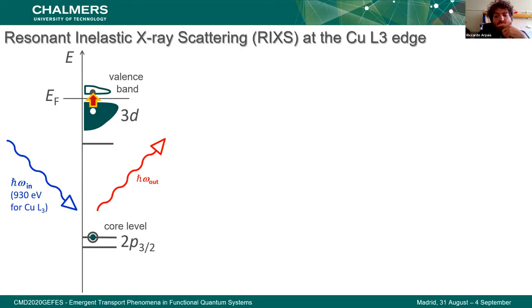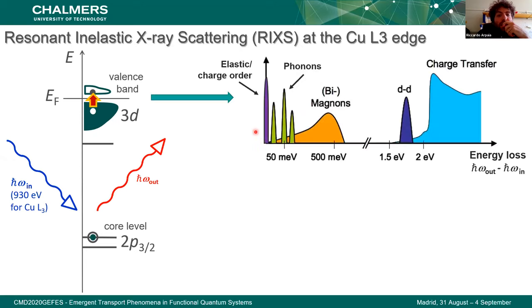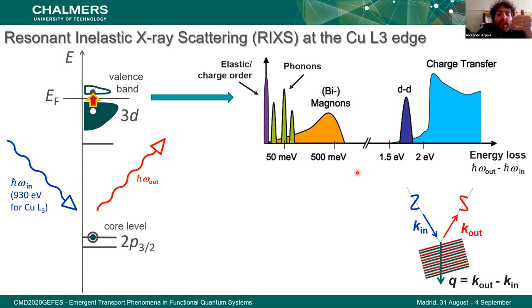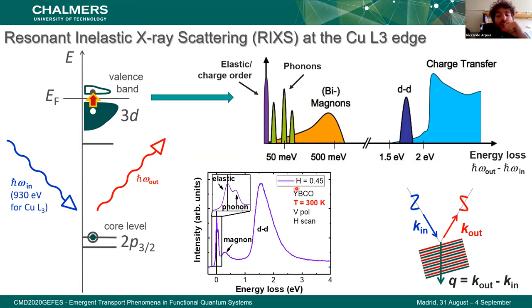Depending on the energy loss between the incoming and the emitted photon, we can study different excitations. In particular, if the scattering process is elastic, we can have access to excitations that are due to charge, so to the charge order. Vice versa, from the inelastic part of the spectrum, we can have access to several excitations: of the lattice, the phonons; magnetic, the magnons; and orbital, so the excitations and charge transfer. In RIXS, we can control not only the energy of the photons, but also the momentum of the generated excitation. This is done by moving the sample or detector with respect to the incoming photon. Finally, this is a typical RIXS spectrum of YBCO at the copper L3 edge that shows all of the excitations that I previously mentioned.